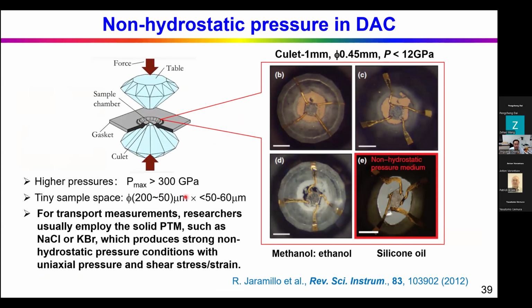And actually most research groups using diamond anvil cells normally use a solid pressure medium, such as sodium chloride or potassium bromide, for the transport measurement. This will produce strongly non-hydrostatic pressure conditions with uniaxial pressure and some shear stress or strain. So this will influence the transport property significantly. To illustrate such non-hydrostatic pressure, I found some pictures from this paper.